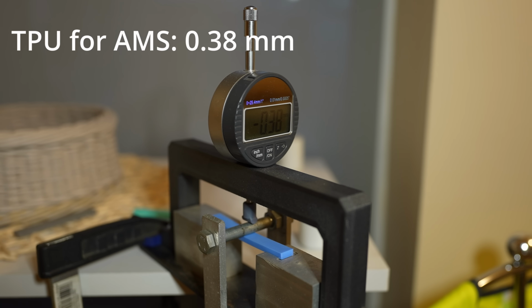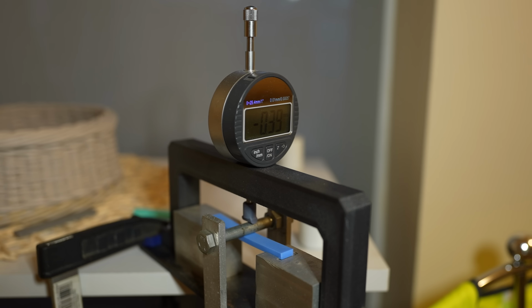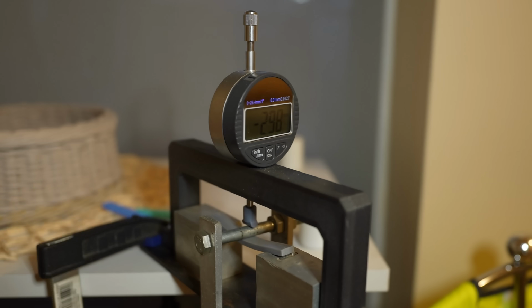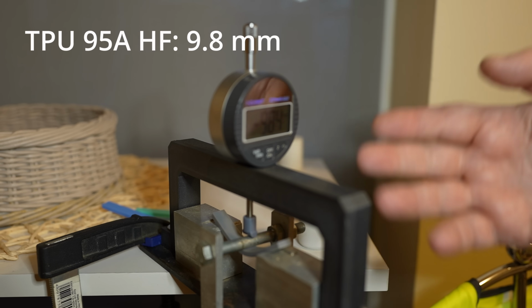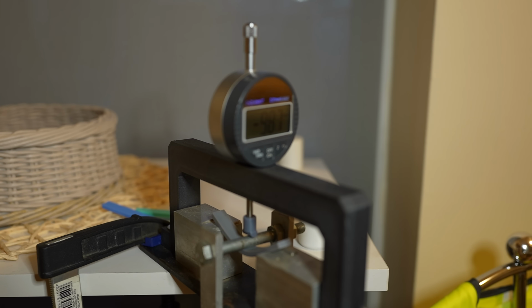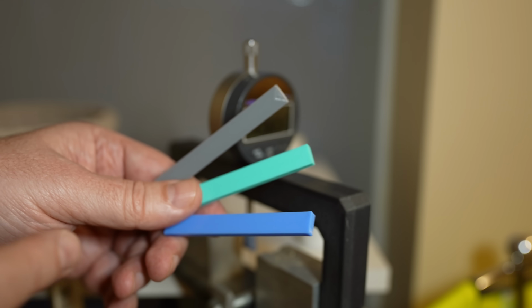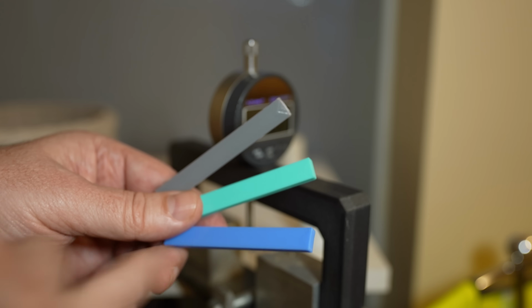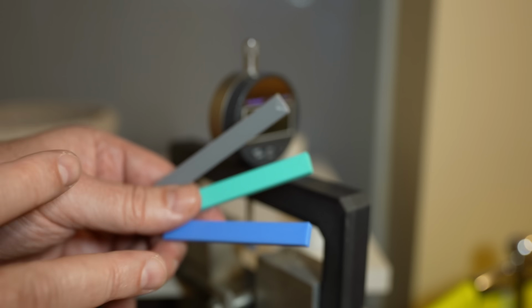Minus 0.38 millimeters. This is TPU 95A, and it deforms even under this holder only. And now I'm placing the weight. More than 9 millimeters, and it is still deforming. According to this flexibility, this TPU for the AMS is closer to the PLA instead of 95A.